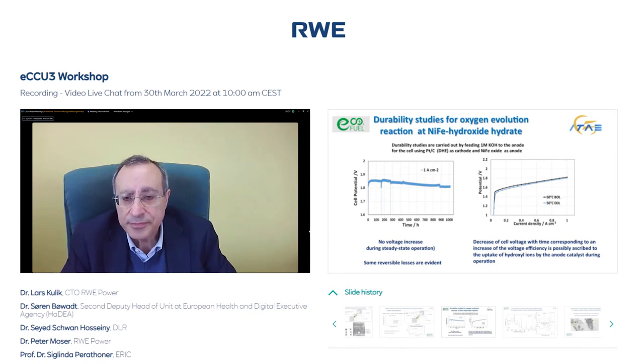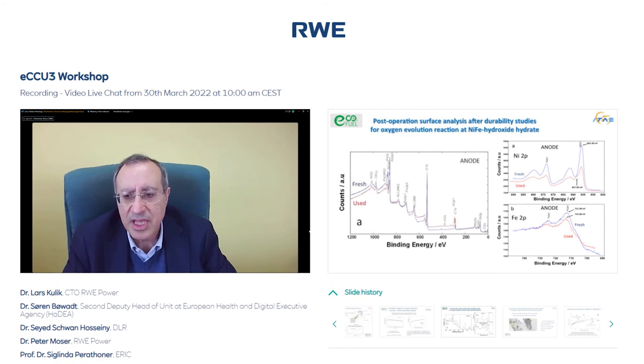Slide number 11, please. So in this slide, we can see some durability test using this nickel iron hydroxide hydrate, 1,000 hours at 1 ampere per square centimeter, and we have a cell voltage of 1.8 to 1.85, and also some small decrease of cell voltage over time. That means an increase of voltage efficiency. And if you compare the polarization curves, beginning of life and end of life, we have essentially the same results. So this is an extremely stable electrocatalyst, highly performing, but also characterized by excellent stability.